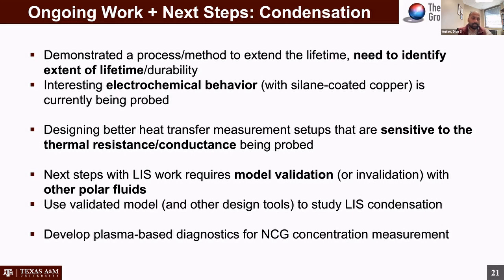With regards to the coating work, we still have to identify the extent of durability. 460, 500 hours doesn't cut it for industrial applications where they want tens of thousands of hours or 10,000 to 15,000 hours of durability. And that's some aspect that we're currently working on.